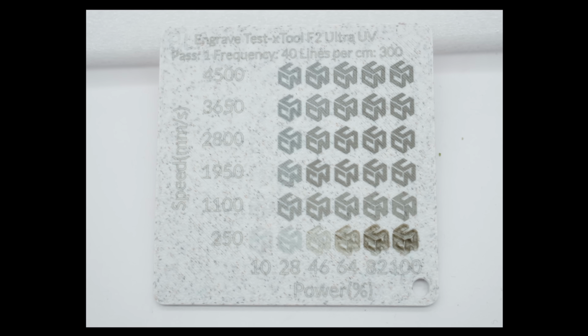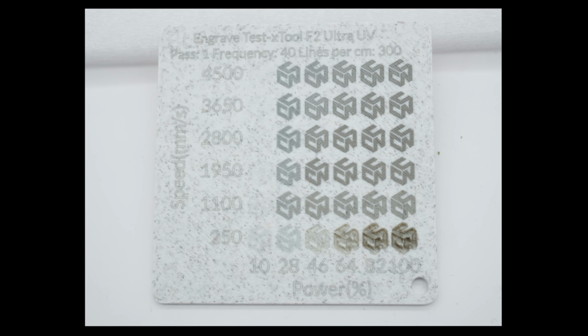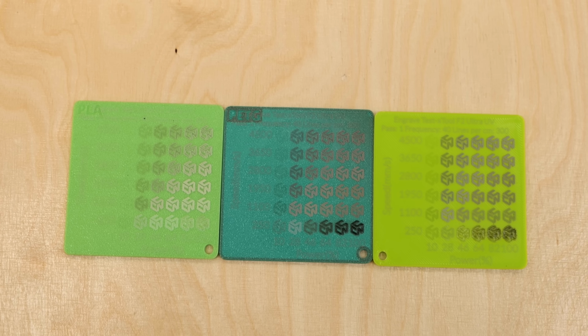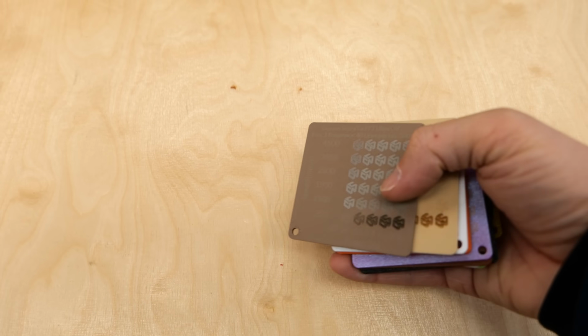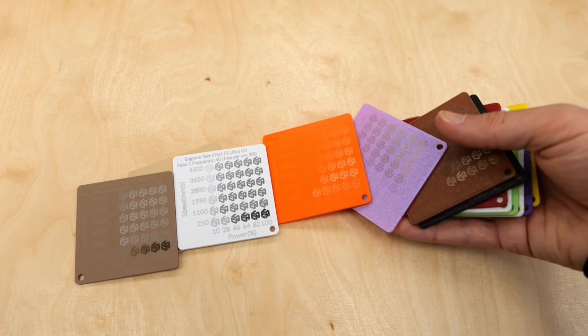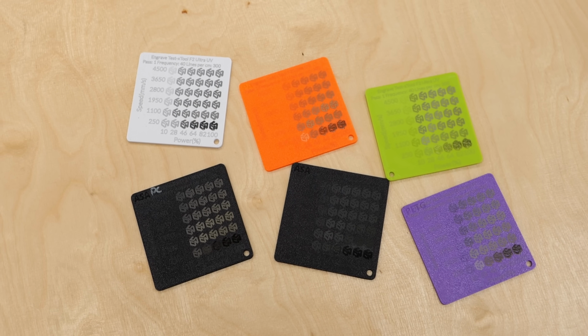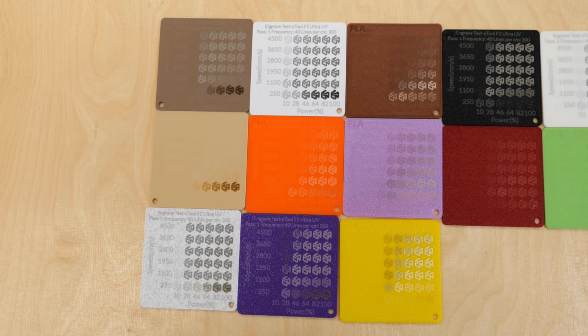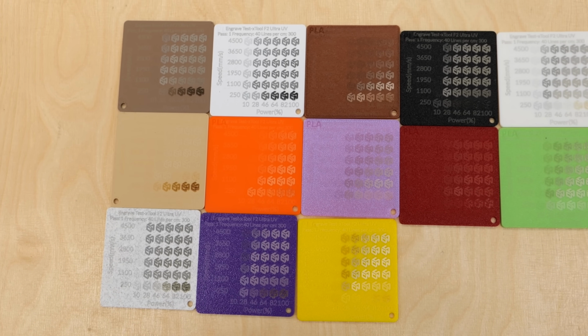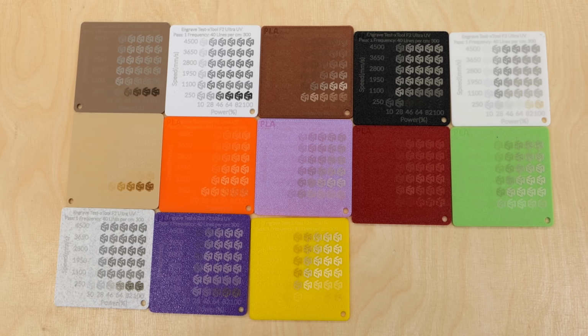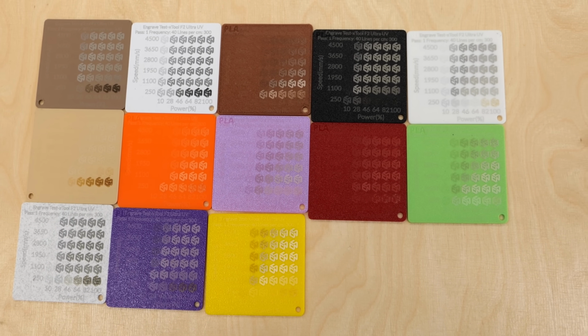That brings me to one of the most important lessons for this whole project. The marking quality often depends more on the pigments and the additives than on the base polymer. Most of my samples were PLA, but I also got very similar results on PETG, ASA, TPU and polycarbonate. The marking result was driven much more by the color and pigment system than by which polymer it was, at least on the UV laser.